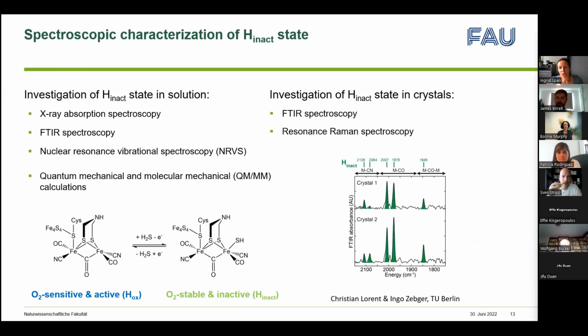So we determined using X-ray crystallography that we have a sulfur species or a thiol binding to the substrate binding site. We also have additional information, spectroscopic data on the H inact state. We have, as mentioned previously, X-ray absorption spectroscopy, FTIR spectroscopy, NRVS. We complemented the spectroscopic studies in solution with quantum mechanical and molecular mechanical calculations.